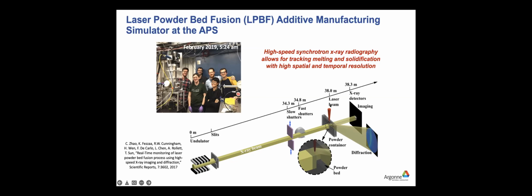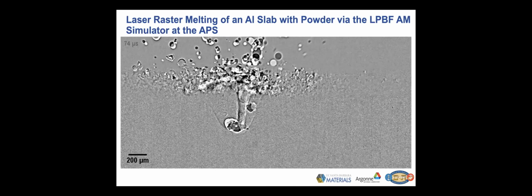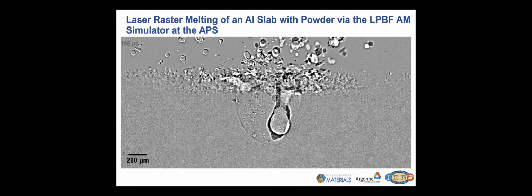Basically the laser beam comes down, impinges on the sample, and creates either a molten metal pool, a spot melt, or a raster. And then we can do real-time imaging and diffraction. Usually we're optimized for one of the two, and in our case, we're optimized for imaging. Diffraction might be something of interest if you want to look more at solid state transformations in an alloy like Ti-64, just as an example. But this is the typical type of information that we can obtain.